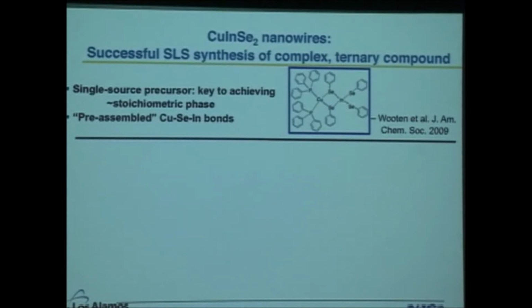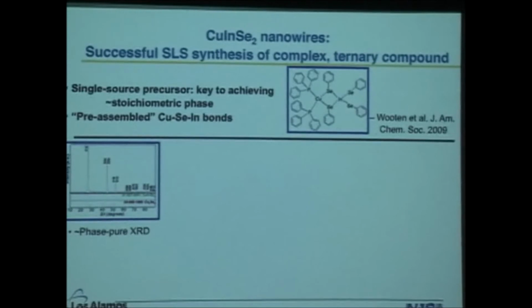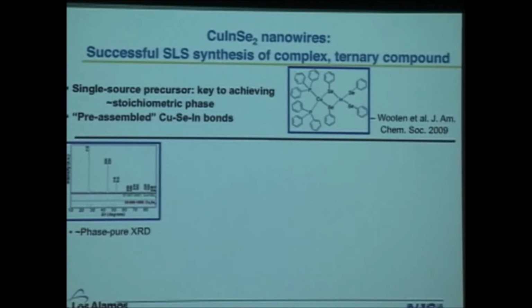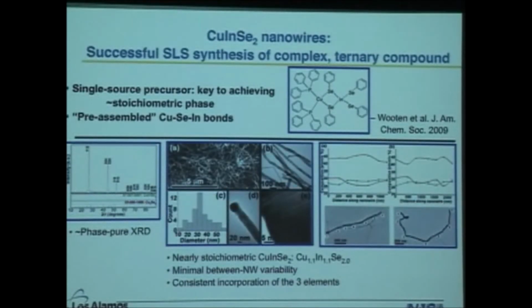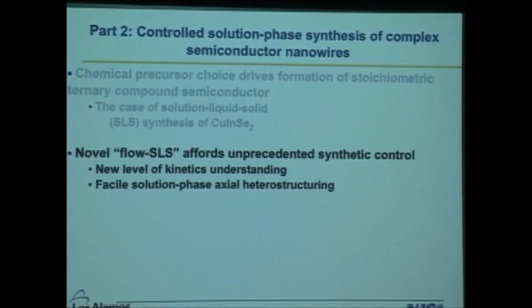This is a precursor that's commonly used in CVD synthesis of thin films, for example, but we can put it in solution, and we effectively have pre-assembled copper, selenium, indium bonds, and this indeed allows us to create phase pure material that was nearly stoichiometric with minimal nanowire-to-nanowire variability, so fairly constant results. They're not terribly pretty, but not too bad, and there's a consistent incorporation of all three elements. So anyway, that was quick.